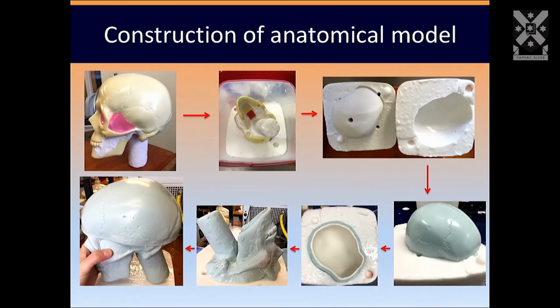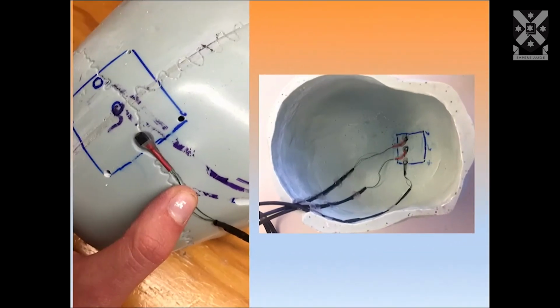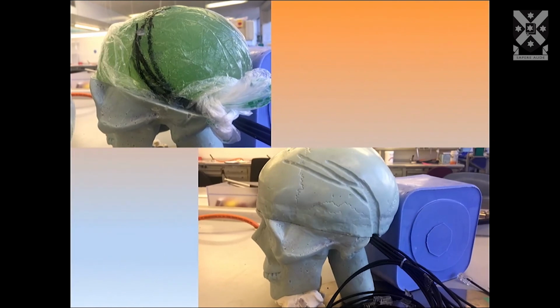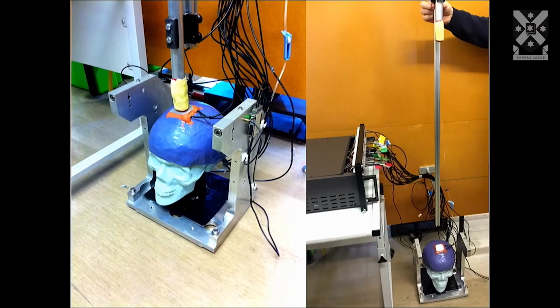The next phase was to a full anatomical model, and we duplicated a human skull and then incorporated into it the various layers that I've just described, with accelerometers to be able to capture what was taking place when impacted. And there's the brain going in and then the top going on. And this then resulted in this model where we were able to then, with a drop rail, have the same amount of impact force as we had achieved.